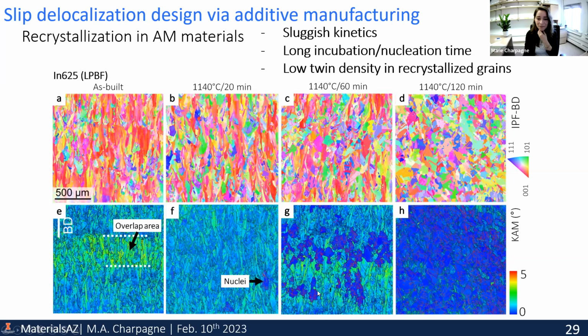And you can see that the distribution of these nuclei for recrystallization is very sparsely distributed. So in order to get this bimodal microstructure like we had in the Waspaloy alloy, it's actually more challenging than we thought. So we're working on this and we're designing new strategies for printing that I like to call print to recrystallize, where we not only print materials with the aim of having them fully dense, but we print them with the aim of maximizing the number of nucleation sites. So that implies that we need first to understand where nucleation happens. And this is a daunting task because of the very high complexity of the microstructures.